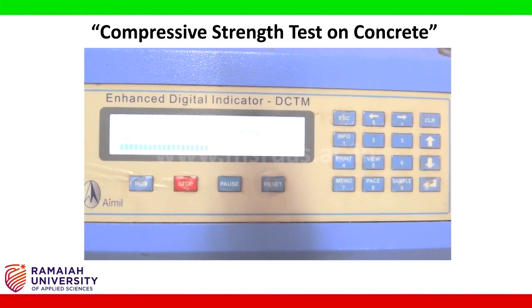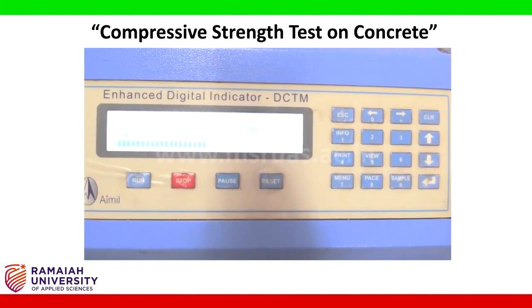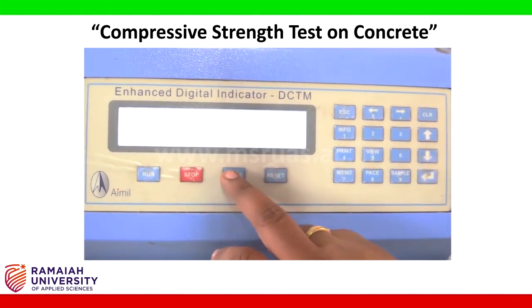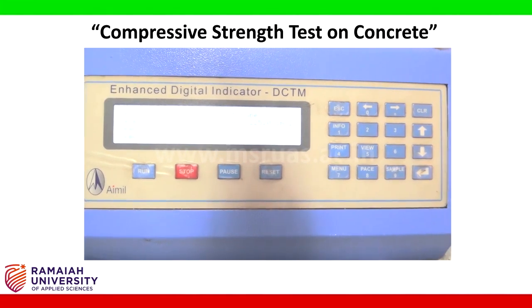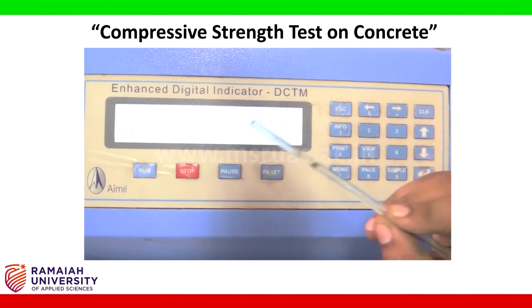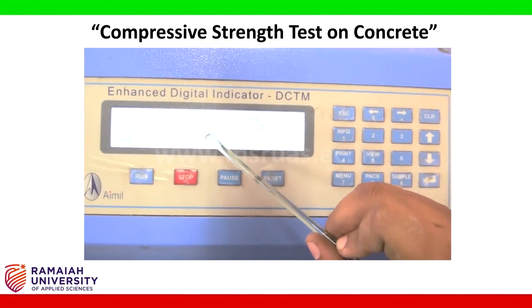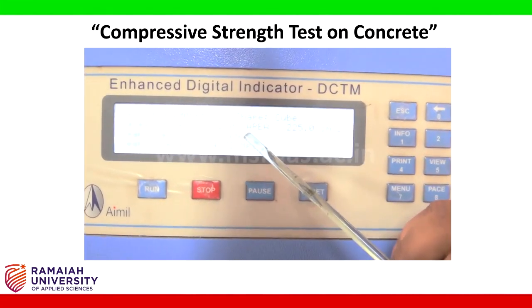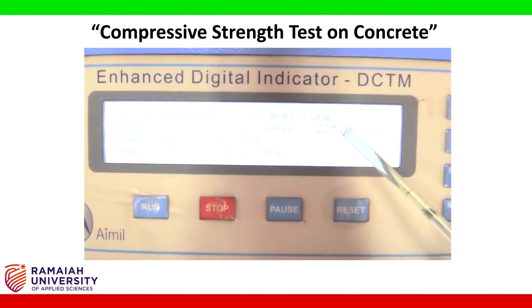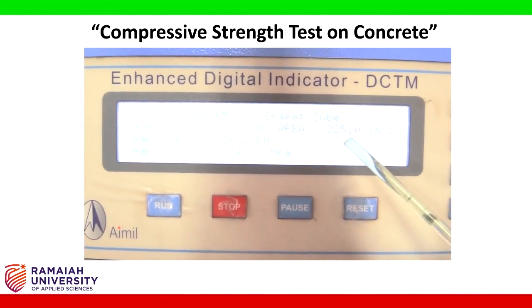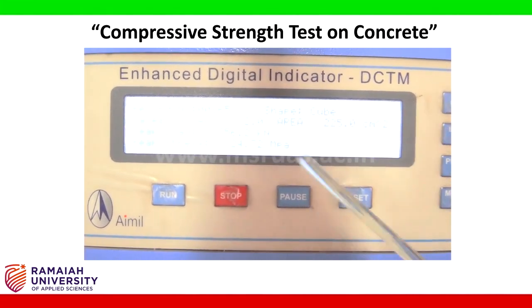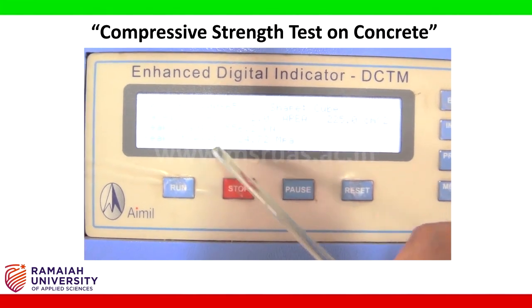How are we going to observe? If you observe, there is an increase in load and then a decrease in load. It went to 500 and then dropped, which gives an indication that the sample is broken, and it gives you the peak load, that is 556.2 kilonewton. I already fed the cube dimension, 15 cross 15, that is 225 cm square. We have a provision that automatically gives the compressive strength, that is 24.72 MPa.